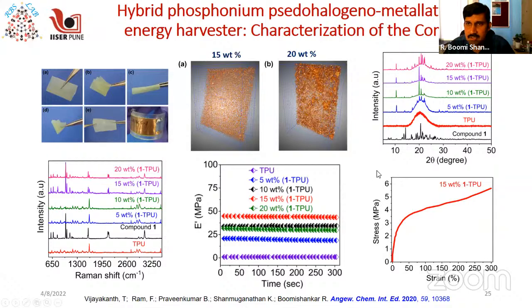Then you can also measure the crystallinity of the composite with powder X-ray techniques. We can also determine the characteristics of these composites using the Raman technique, where the peaks due to the polymer as well as the compound are present in all the composites. We can also test the viscoelastic, or stress-strain, relationship of the material using a mechanical force technique, by subjecting them to a dynamic mechanical analyzer. This is called viscoelastic measurement, where E prime is your elasticity of the material, and E double prime tells you the viscosity of the material, which I have not shown here.